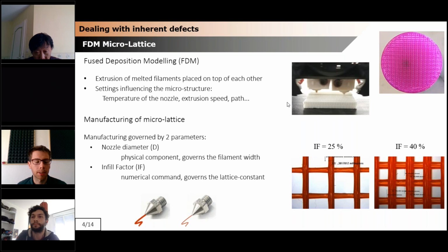So we 3D printed this material using the fused deposition modeling technique. A very simple method where you extrude a melted filament and place them on top of each other. So it really suits the printing of such material. And again, with this technique, you can easily tune the lattice constant of the material, so the distance between the filaments, by changing one parameter that we call here the infill factor. Here you see for two different infill factors the resulting microlattice. For those who are more used to felts, changing the infill factor will correspond to changing the compaction rate of the felt.